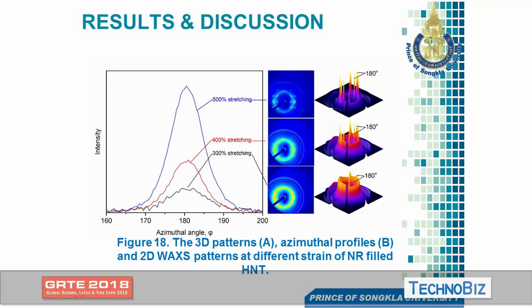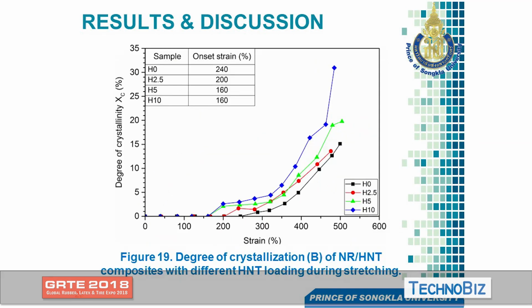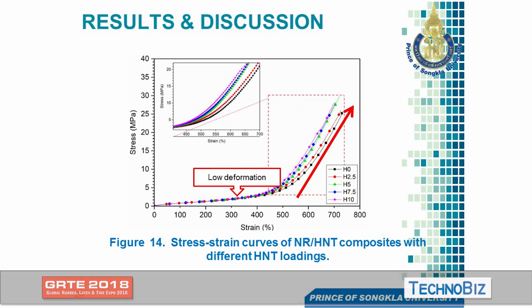This is the 3D image. Okay, we also studied the degree of crystallinity, whether there is more crystallinity as mentioned before or not. So as we can see here, when we increase the amount of HNT, the onset is at lower strain. The crystallinity of the natural rubber filled with HNT started to occur earlier. Comparing the unfilled one and the filled one, this figure is in very good agreement with the stress-strain curve.